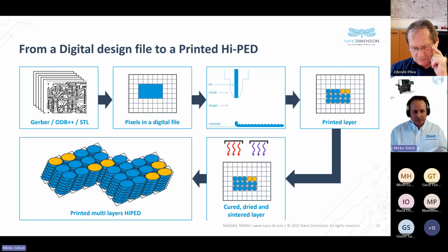How we do that? The machine supports Gerbers, ODB++, STL files, Excellons, and converts the 3D design in layers. So the machine slices the design in layers of 1.25 micron of thickness. Each layer is basically a matrix of pixels, and each pixel is a droplet that we are jetting of conductive or dielectric material. We do that layer by layer, and we grow up the structure in this way.